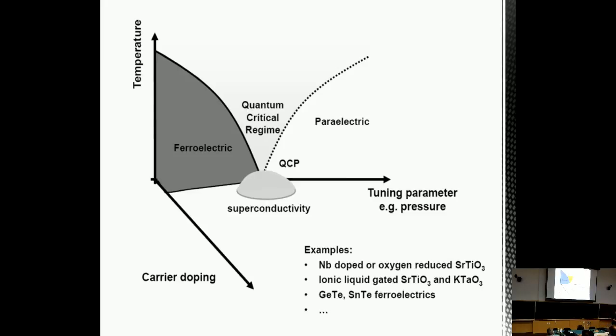So just making it look a bit more three-dimensional, it looks like this. Ferroelectrics are insulators, but when you put in electrons, they can still maintain a polarization, and you can actually tune the ferroelectric transition to 0 with carrier density. So there's a third axis here. And when you do that, you have a dome of superconductivity within this model forming close to this point. And we see this as a route for searching for new superconductors mediated by these hybrid polar modes. And I should point out that the model also works in potassium tantalate, which is also a quantum ferroelectric, where you can gate carriers using the ionic liquid method, and you also see a dome of superconductivity in this case.